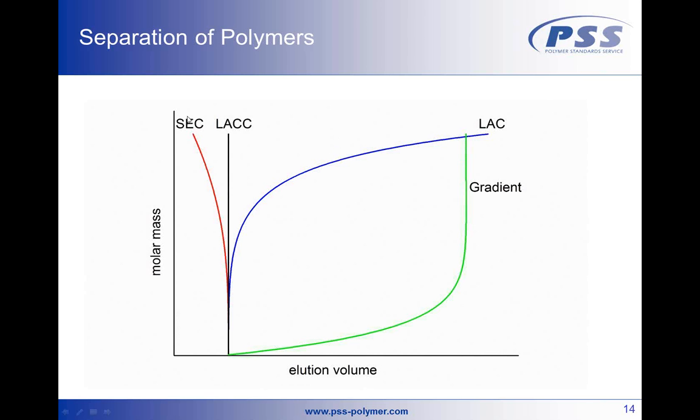And if you now have a polymer chain which has end groups and repeating units, and you make the repeating units chromatographically invisible, meaning they don't contribute to the retention volume anymore, then basically your elution or your retention time is determined by the visible part of the polymer, which is now the end group. So at critical conditions we have an option to separate polymers according to the end group, for example, or in general do very tiny differences in structure.